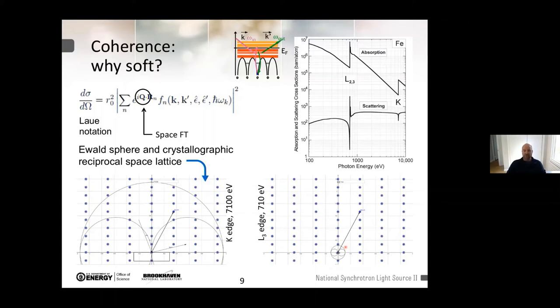So is this worth the case? There are two considerations that should be made from the purely technical point of view. One of which is that having several diffraction points is not always an advantage. For example, it constrains you to limitations due to multiple scattering, which is certainly not a problem in soft X-rays. The other is that, yes, you cannot study the structure, or not directly maybe, but you can study any kind of order that is susceptible to frustration, and as such typically has a propagation vector that is large, but smaller, so it's a structure that is larger in real space. And this is exactly what typically happens, luckily, to electrons in complex systems, where complexity is one, and frustration is one of the points. Certainly, or very likely, you have some propagation vector that sits in the surrounding of the zero propagation vector itself. So it can maybe be studied by soft X-rays. And this is exactly what we are interested in.